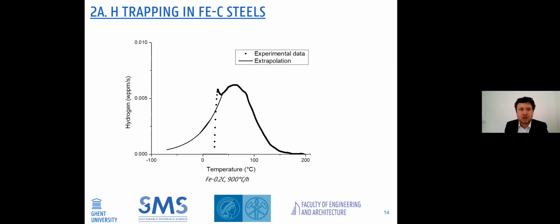As you can see in the experimental data, we have quite a large jump in the beginning. This is because we keep the time in between charging and testing as short as possible, because we don't want to lose hydrogen. If you wait longer times, you don't have this quick jump, but then you also lose important information. So we keep the time in between charging and testing to 1 minute, 1 minute to clean and dry our sample, and then we can implement it into the furnace. But because of the very high diffusion, you can see a very quick jump at 20 degrees C. And this is then followed by a slow decrease.